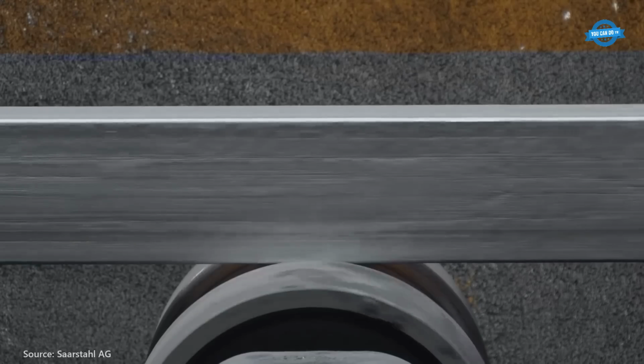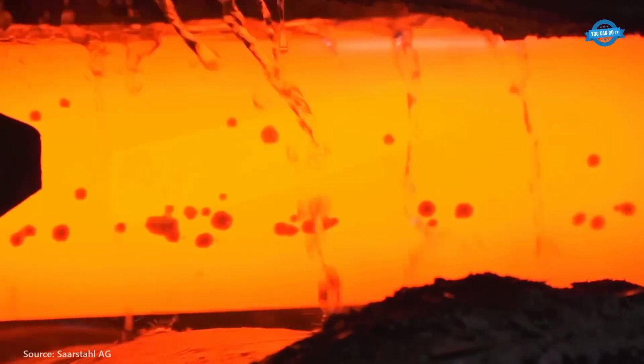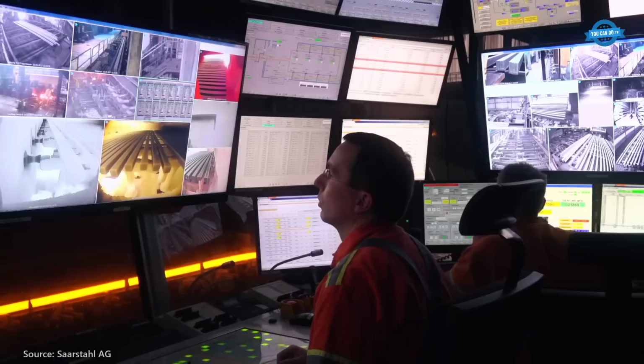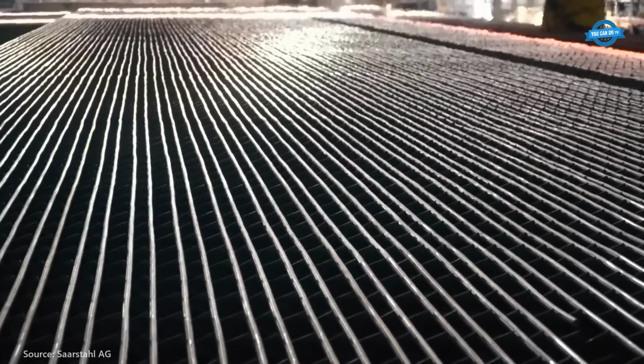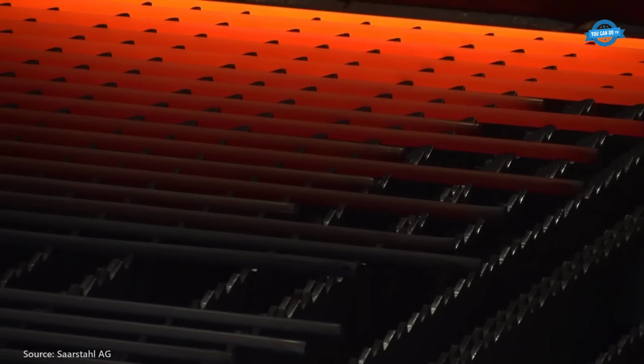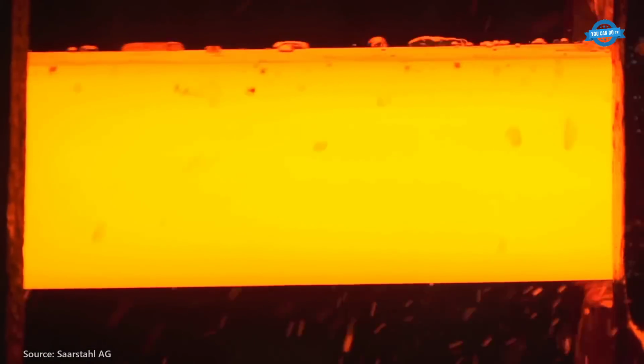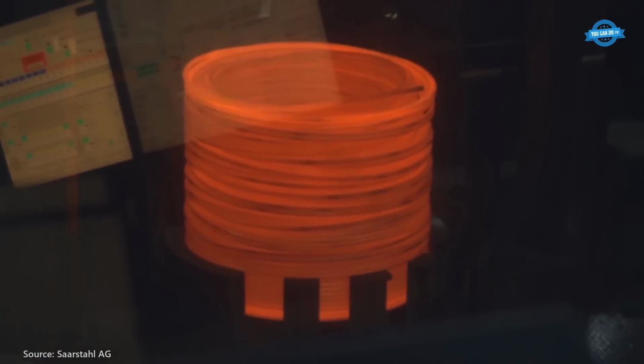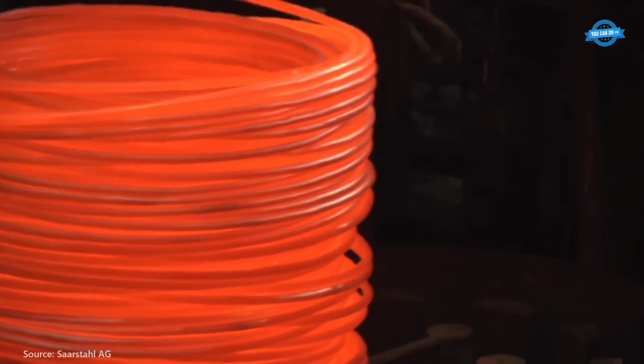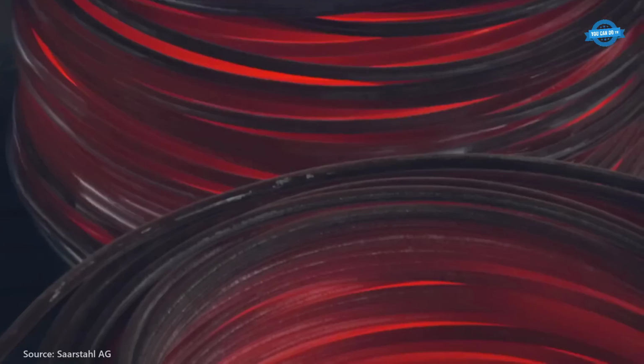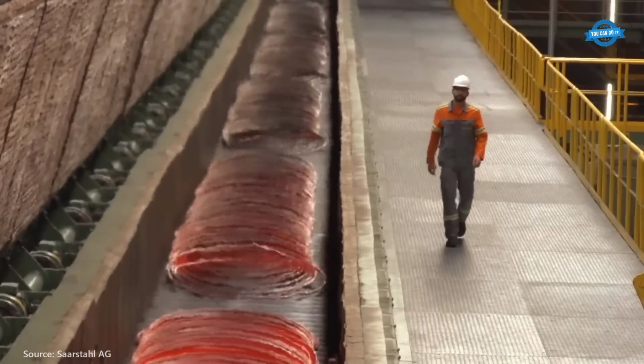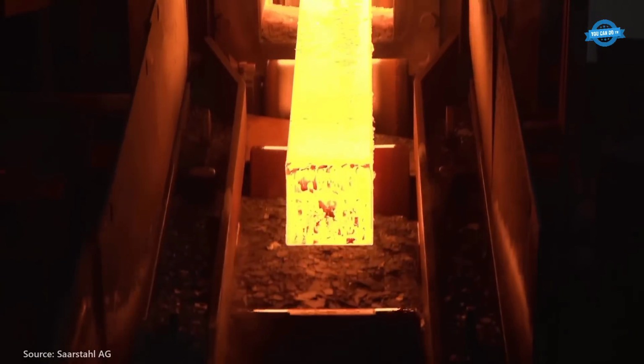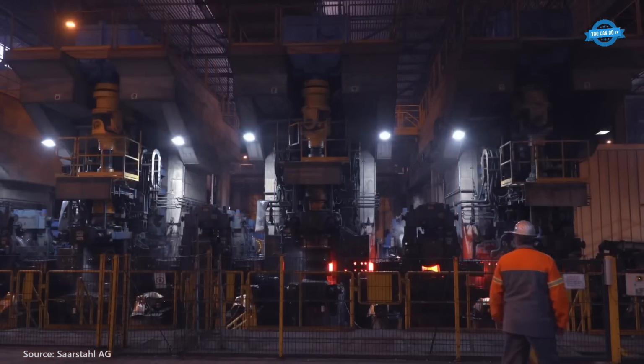Continuous casting. The refined liquid steel is cast into billets or blooms using 4 continuous casting machines. Saarstahl was one of the first companies to implement MSR technology, which significantly improves the internal quality of the steel by reducing central segregation. Burbach Rolling Mill produces wire rods with diameters ranging from 4.5 to 18 millimeters. Rolling. The cast products are then processed in various rolling mills to produce the final steel products.